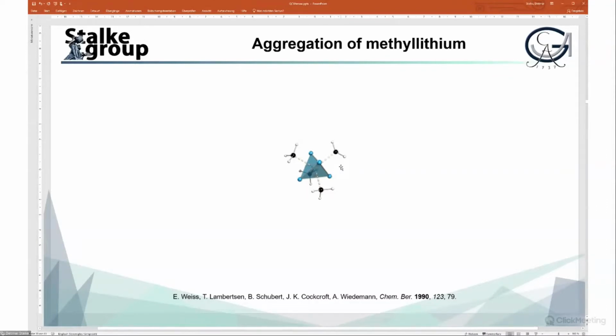So they try to avoid the lithiums, and what they do is aggregate to this tetrahedron. We have a backside attack from this methanide from the next tetrahedron and vice versa. We do that in a strand of molecules, which is in fact the room diagonal of the methyllithium structure.